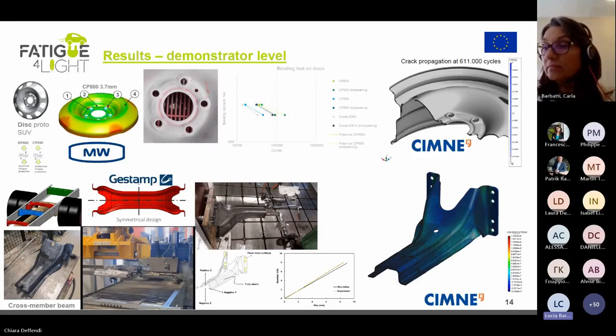For some materials, the forming process induces beneficial effects towards the fatigue behavior, while for some other materials, the stamping cycle induces detrimental effects. So it's a very interesting result, I would say. After that, Magnetto Wheels performed a quite extensive experimental campaign. They did a lot of work here when they studied the bending test on the discs for different materials with different types of treatment, with shot peening, without shot peening. And on CIMNE's side, we also modeled these solutions to see if we were obtaining a good approximation of the fatigue life with respect to the experimental life, which I can also advance that we did.